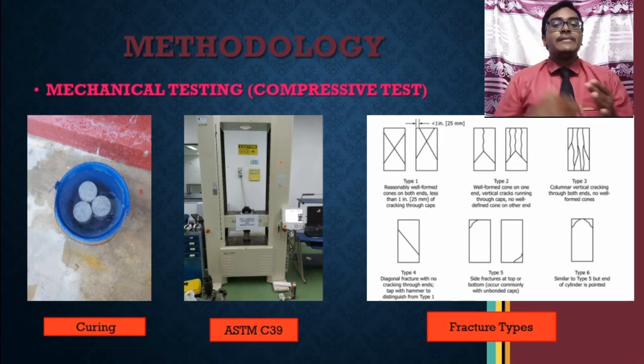Okay, before moving to the mechanical testing, the concrete must be cured. As soon as the concrete is hardened, curing should begin and last for at least 7 days.